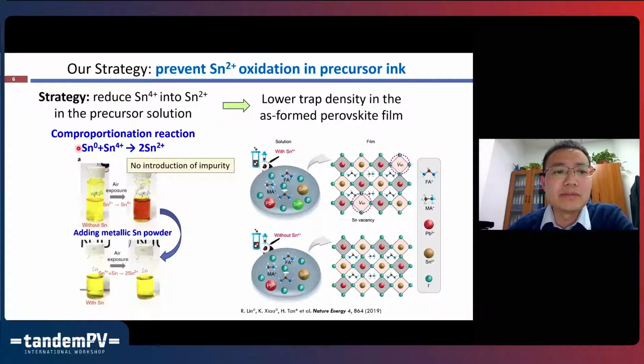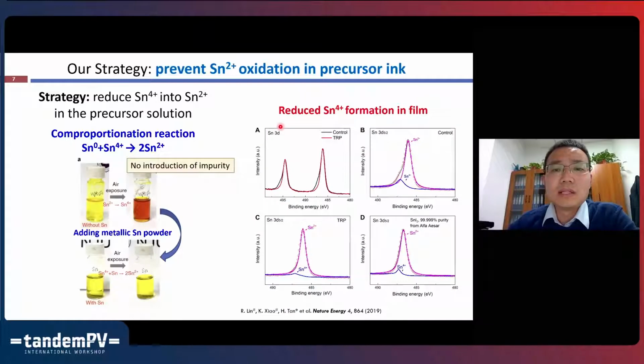We can add a small amount of metallic tin powder in the precursor solution. This metallic tin powder has a very strong reduction ability, and it can reduce the 4+ tin ions back to the 2+ ions. That is what we want. From this strategy, we supposed that this would result in lower trap density in the final perovskite film. We also measured XPS spectra, and we clearly see that for the perovskite film made from the tin-reduced precursor solution, the oxidized tin content is considerably reduced. And this gives us very good benefits in the perovskite film.